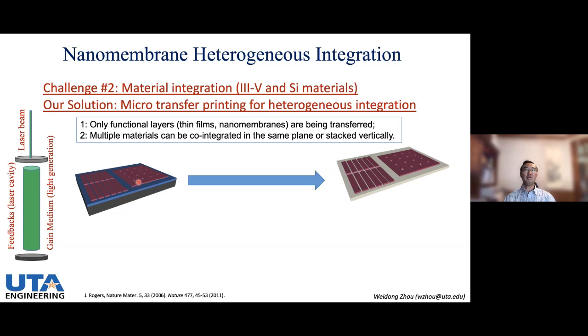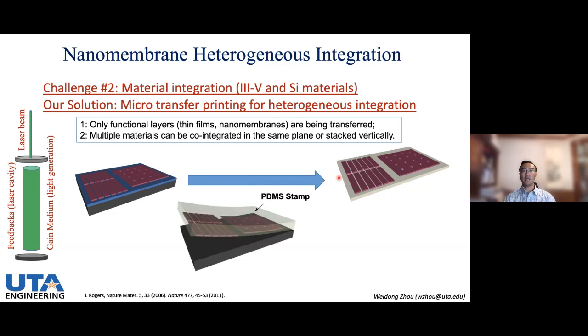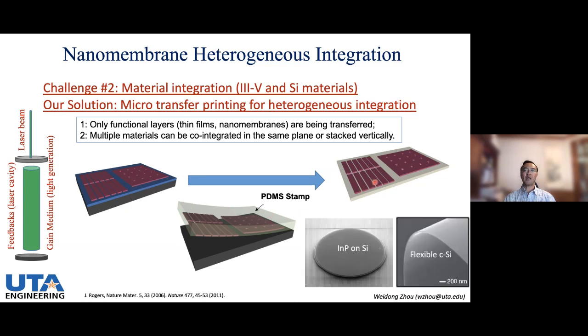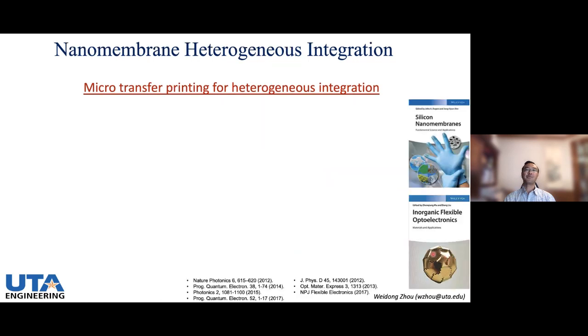So what do we do here? We simply release the functional layer from a substrate so that we can put it onto another material. For example, we pick up this thin layer of silicon using a PDMS polymer stamp, and print it onto a different substrate. By doing so, you can have III-V thin-film integration onto silicon, or you can even make flexible crystalline silicon. I don't have time to talk about it. That's another very interesting area of research.